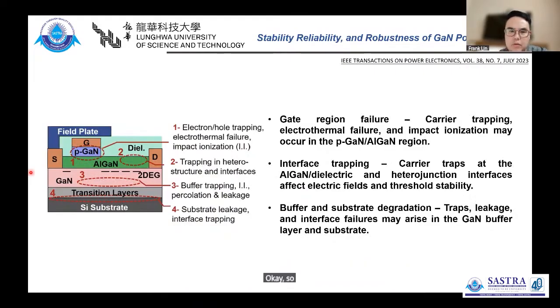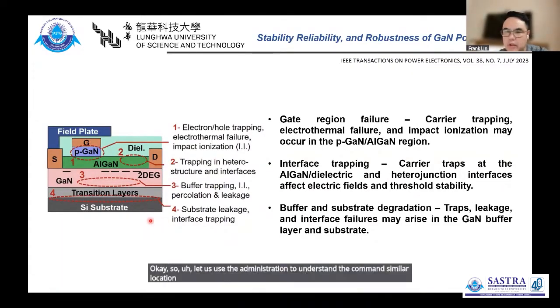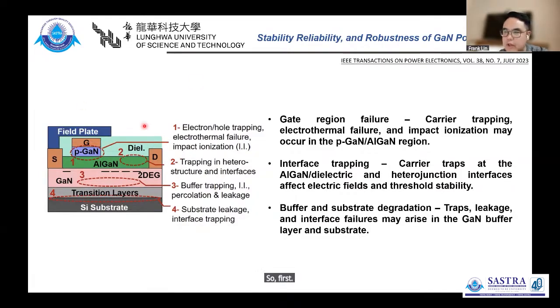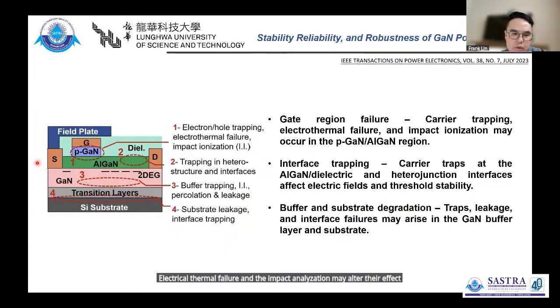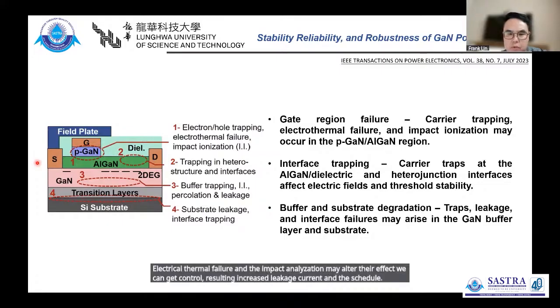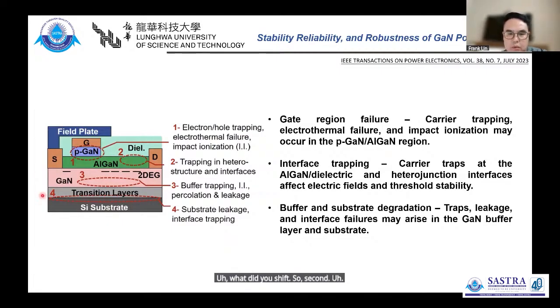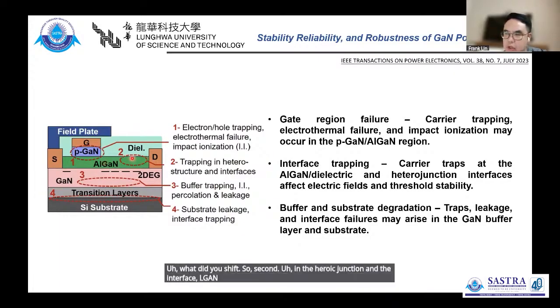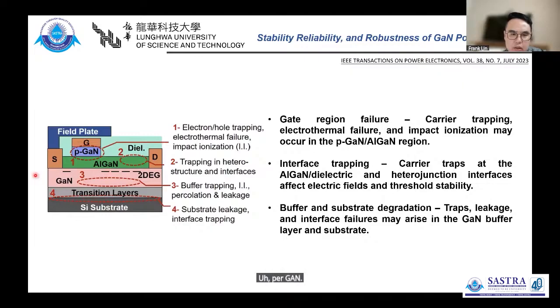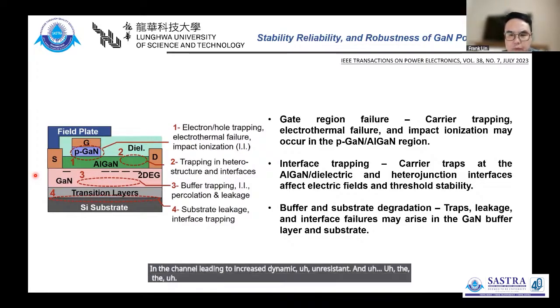Okay, so let's use the illustration to understand the common failure locations and mechanisms in the GaN HEMT device. So first, in the gate region, in this area, electron and hole trapping, electrothermal failure, and impact ionization may occur. Their effects weaken gate control, resulting in increased gate leakage current and threshold voltage shift. So second, in the heterojunction and the interface, AlGaN and the dielectric-to-GaN interface traps affect the concentration and the distribution of the 2DEG in the channel, leading to increased dynamic on-resistance and deterioration of the output characteristics.